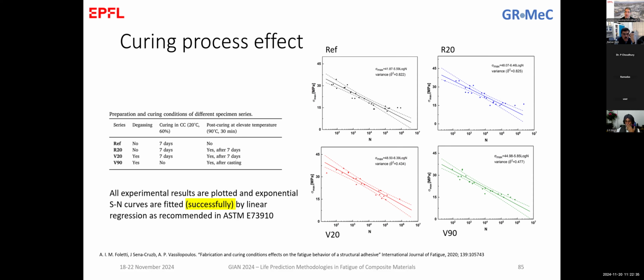You can have an increase of the properties even in the first year, a year, not days, of the adhesive during operation. So here we try to see if it is probably better to do some post-curing during fabrication to help the material achieve the maximum properties faster. So we did 4 different curing conditions for the fabrication.